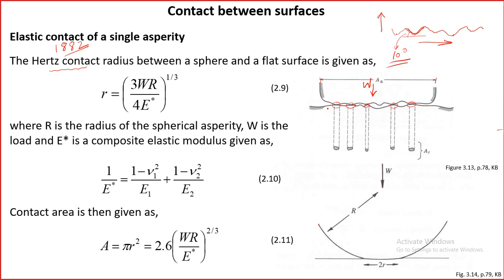The strains are small, which is also fine. These strains will be small because we don't assume that the elastic deformation will be too large, because beyond a certain point it will go into the plastic range. Each solid can be considered as an elastic half space in the proximity of the contact region. So this is a fully elastic region. Another assumption required is that the contact surfaces are frictionless. So there is no friction here, which is actually not true. For real surfaces, there will be some friction. So those are the assumptions of Hertz analysis.